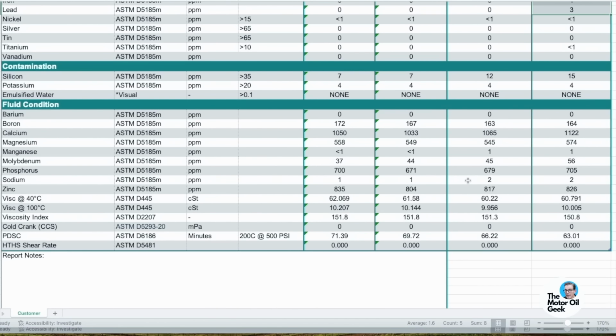Come down and look and say, okay, here's what else we got going on, because one thing I didn't mention is there is some silicon in the ring as well. That coating has some silicon in it, so we can't just say that silicon is only dirt. The silicon is also embedded in the ring, so while the titanium levels are very low, some of that silicon increase could be coming from the ring wearing, and so that less silicon in this sample could also be an indication that there's just less wear going on overall, which kind of correlates with the rest of the results.